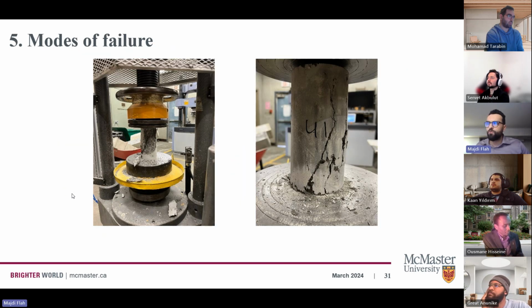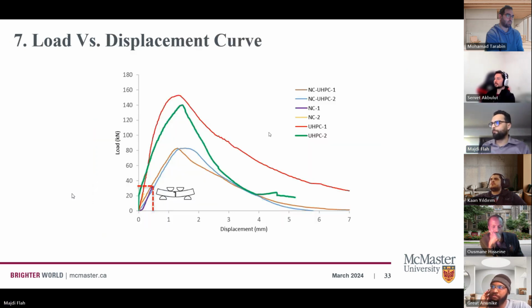Talking about the modes of failure, in the picture on the left, which is the cylinder for the compressive testing, we can see that for normal strength concrete, there is a big spalling. All the area is being crushed, and all the chunks are being distributed over the area there. However, when we look at the UHPC specimen, we can see that the fibers are doing a very good job trying to limit the cracked area and trying to limit the spalling area as being shown in here.